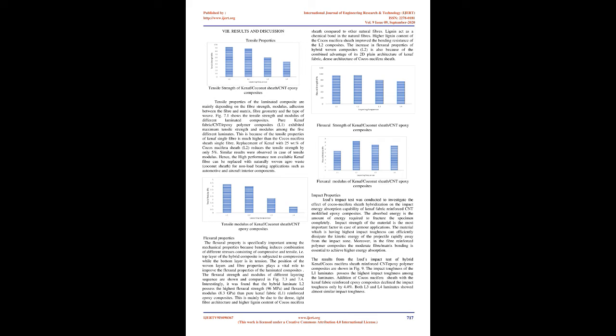6. Fabrication of composites. Laminated hybrid composites were fabricated by using simple hand layup method followed by hot pressing. A wooden mold of dimensions 200 x 200 x 3 mm3 was used. The mold was first cleaned and applied with a releasing agent, silicone spray, to prevent the adhesion of laminated composites with the wooden mold. After curing it improved the surface finish of the composites. Epoxy resin and the curing agent were mixed for 15 minutes with 2:1 ratio respectively. The overall fiber/matrix weight ratio was kept as 45/55.